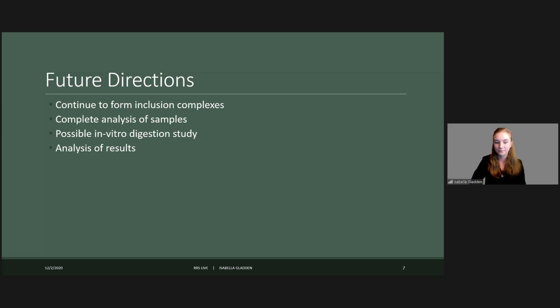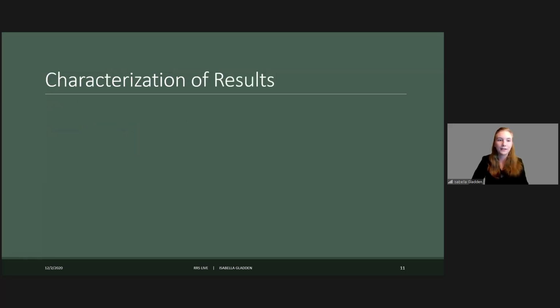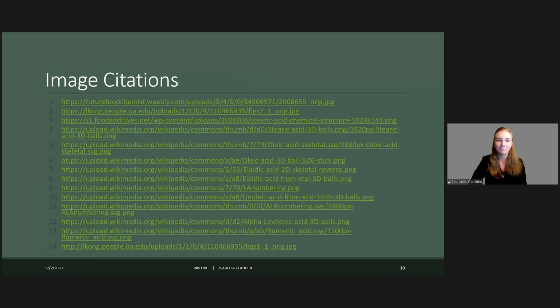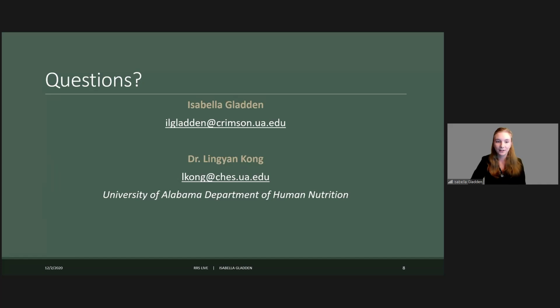As a characteristic, how do you determine the thermal stability of the inclusion complex? So I believe it was slide 3. So the stability, as shown on the slide from our previous results, essentially with the differential scanning calorimetry, you look at how high the temperature has to go in order for the inclusion complex to dissociate and break apart into the guest and the starch.